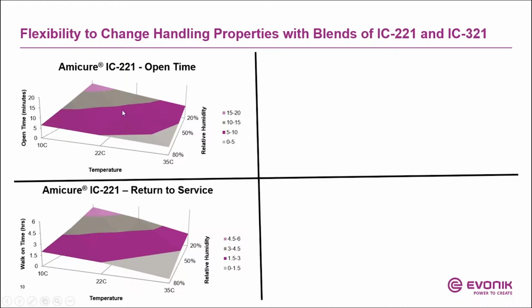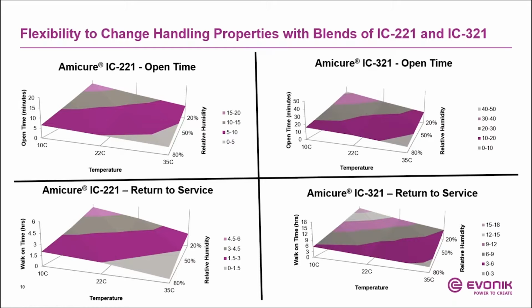But over here, in terms of lower temperature, lower humidity, you can see you get a good amount of working time, and then even with return to service, you're still getting fast return to service. So really, with Amicure IC221, the reason you would use that is when you're working in these kinds of conditions of low temperature, low humidity. Okay. Now going to the other extreme is Amicure IC321.